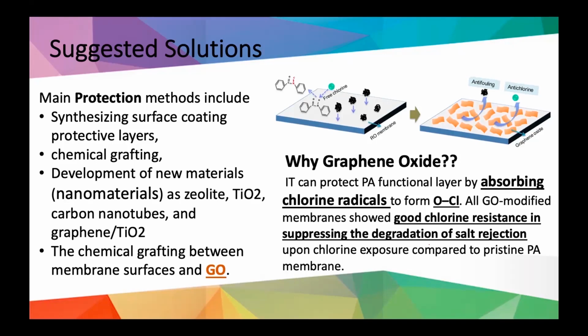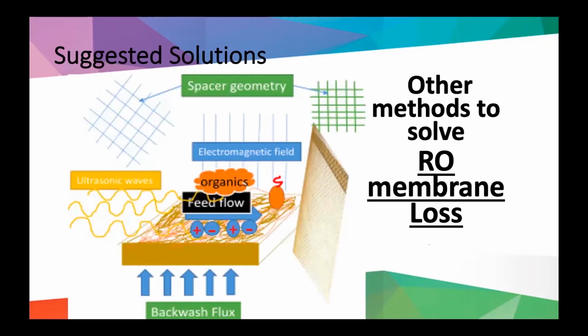But to absorb the chlorine radical, the graphene needs to have some linkage, some cross-linking, some functionalization in the surface of the membrane, and how to get the suppression, how to get good chlorine resistance in suppressing the degradation of the salt rejection. Because as we get the chlorine resistance high, we can lose some of the salt rejection. So this is one of our goals.